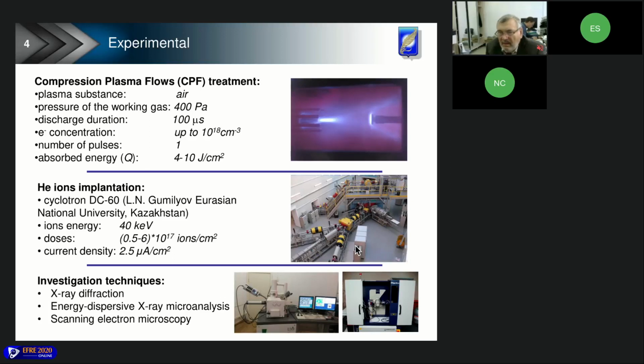Helium implantation was carried out using the cyclotron DC-60, located in Nur-Sultan, Kazakhstan, at Eurasian National University. The energy of ions was 40 keV, and doses were varied up to 6 multiplied by 10 to the power of 17. Well, let us consider the investigation results.